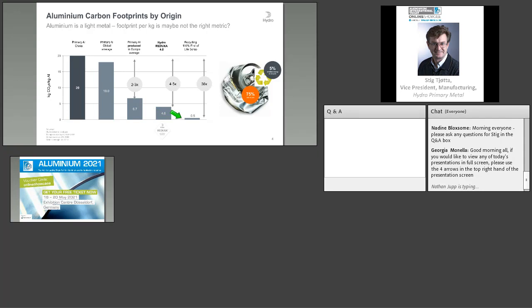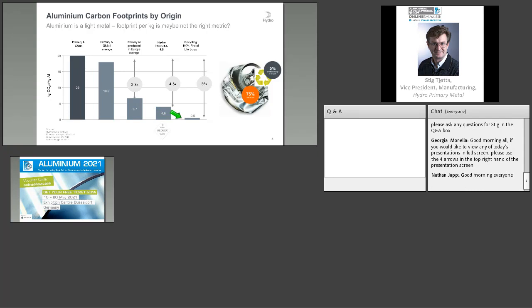And if we then go to recycling of end-of-life scrap, aluminium based on 100% recycling will only have a carbon footprint of 0.5, which is a staggering 36 times lower than the global average. So I put this up in order to understand that when we do a life cycle analysis of a product, we cannot treat aluminium as an average. We really have to treat it with the source, and it can have a quite drastic impact on the total carbon footprint of any product and vehicles in particular, as we will see.